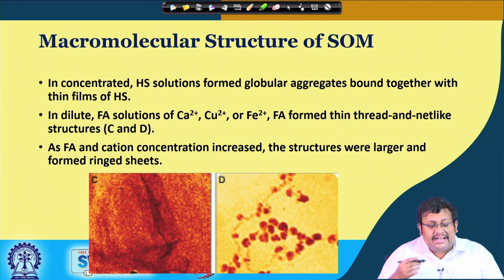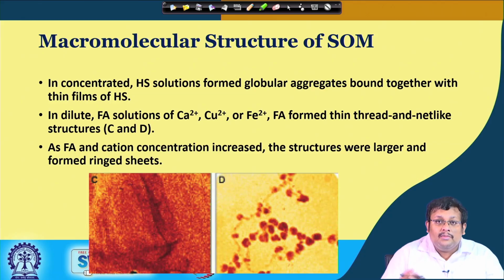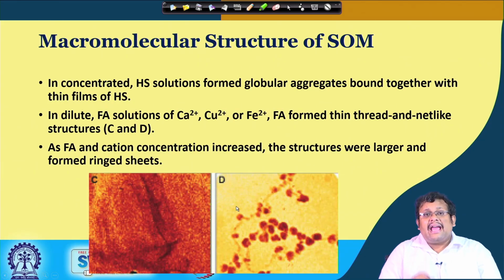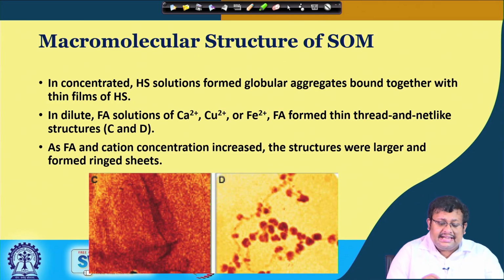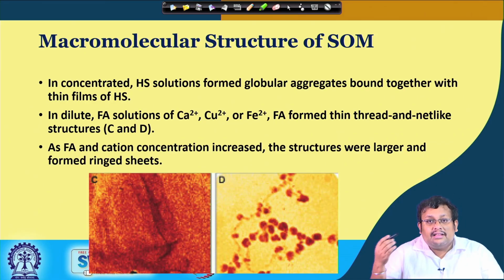In concentrated humus solutions, globular aggregates form, bound together with thin films of humic substances. Now, in these two pictures you can see that in dilute fulvic acid solutions of calcium, copper and iron, fulvic acid forms thread and net-like structures. As fulvic acid cation concentration increases, the structures were larger and formed ringed sheets.